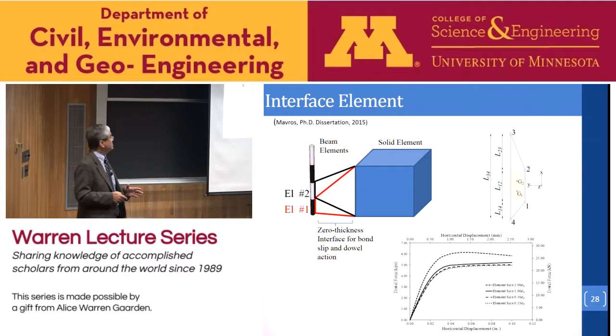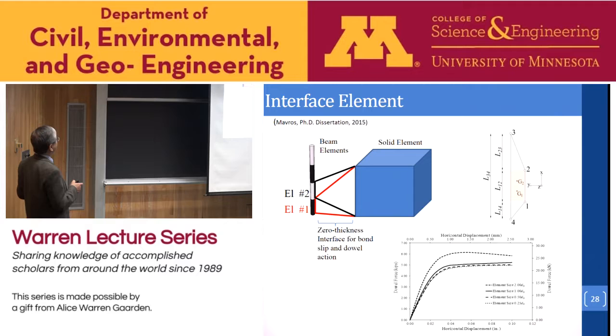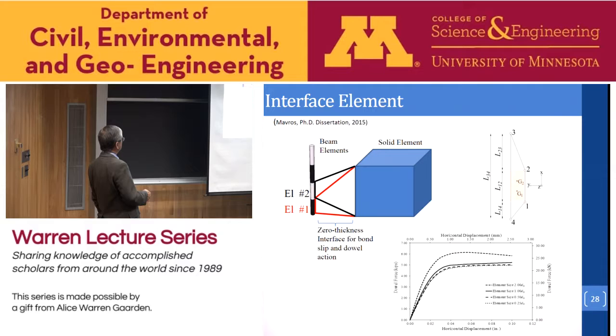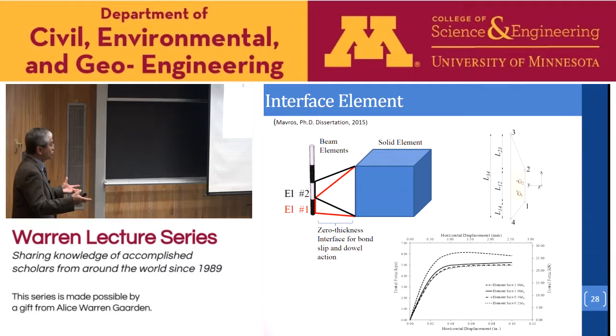So we try to model the behavior of the dowel in the interface. The interaction force between the concrete and the steel is all modeled in this interface using the law provided by Brenner. And also, in order to further enhance the efficiency, we developed a special interface element that allows the size of the bar elements to be different from the size of the concrete elements. That means we can use much smaller bar elements as compared to the concrete elements. The small bar elements are required to model the dowel behavior appropriately, while the failure behavior of concrete can be represented by a much coarser mesh. So essentially, we developed this element, and the interaction of the bar, this is the bar side, this is the concrete side, will be based on the tributary area, tributary length of this bar.